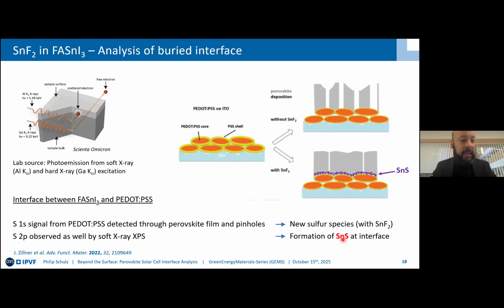And this also led us to the conclusion that it's actually critical to have this PEDOT:PSS in this lead-free perovskite device, which at the time you did not come across many studies that did not have working devices on PEDOT:PSS. And this was something we were able to see by HAXPES, in that case, inadvertently. Just very briefly, tin sulfide, of course, promotes hole extraction, but makes for a very poor mechanical contact, and you have to combat delamination and eventually then long-term stability losses.